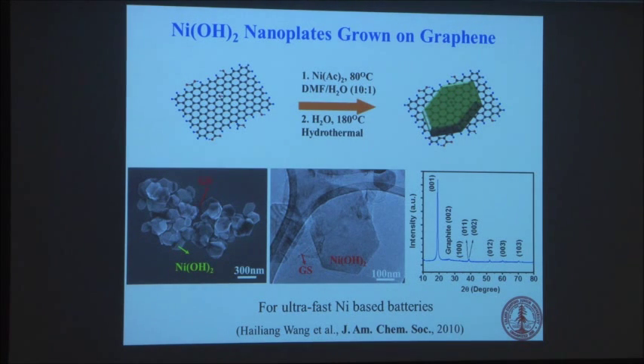Another example has to do with these nickel hydroxide plates. Nickel hydroxide is very, very insulating, so normally its charge or discharge is very slow. But we found that if you grow them on graphene, the charge and discharge can be very quick, and it's actually useful for making faster batteries.